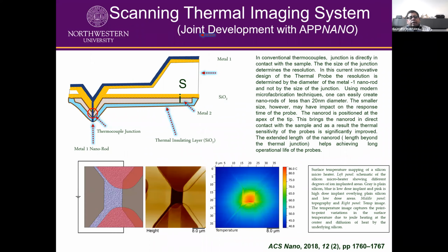Then I will move on to another functional AFM, which is high resolution thermal imaging. I developed this with a Bay Area company, App Nano. In the literature, conventional thermocouple-based scanning thermal imaging systems are not very high resolution, 200 to 300 nanometers. The thermocouple is in direct contact with the sample, and it also picks up lateral heat, which degrades the resolution.